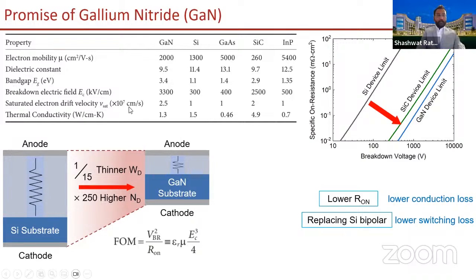So essentially, because of an order of magnitude higher critical electric field and about twice the mobility, gallium nitride has a much better figure of merit compared to silicon. So what this means physically is that for the same rating, or for the same breakdown voltage, your gallium nitride device can be 15 times thinner than a silicon device and can accommodate about 250 times higher doping density, which means that it will have a much lower on resistance for the same breakdown voltage.